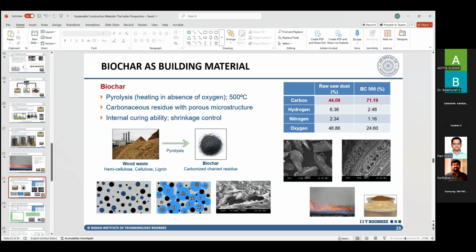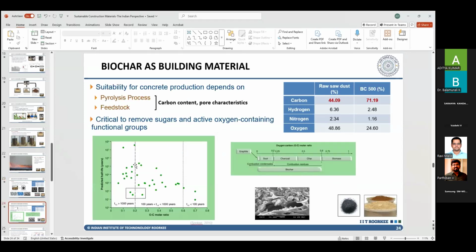But the challenges are the pyrolysis condition, and from where you are getting the source material, the feedstock. Because some organic matters such as peanuts are high in phosphorus. Now if you use these materials, you make a char out of it and then you use it in the concrete, you're adding phosphorus into the concrete, which is not good. We try to limit all the alkalis and such kind of materials when we're using them in concrete. The other thing is how stable your char is, because it's an organic matter, and in concrete we have a big no for any organic matter to go in. You have to ensure that the char that you're using is essentially an inert material.